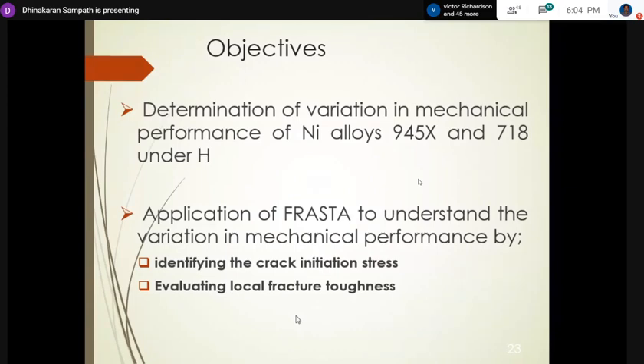So we need to use fracture mechanics specimens, but the industries use slow strain rate tests. So we are going to show why we should move to fracture mechanics specimens. First we did a couple of slow strain rate tests. That's basically a simple tensile test, but at a very low strain rate, like 10⁻⁶ per second. And then what we are going to do is use FRASTA, which is a quantitative fractography technique, to identify the crack initiation stress and local fracture toughness.